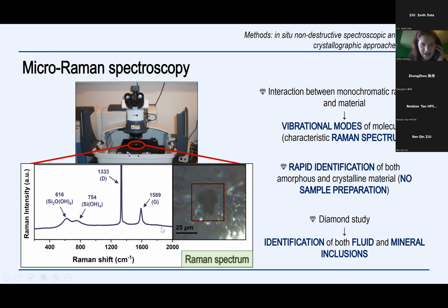And as you can see here, the Raman spectrum consists of a series of Raman peaks or Raman bands, and each Raman peak corresponds to a particular vibrational mode of the molecules that compose the analyzed material. The Raman spectrum can be considered a fingerprint of the material that we are analyzing. For this reason, micro-Raman spectroscopy is used for the rapid identification of materials, both amorphous and crystalline. This is very important. Another important thing is that this method does not require sample preparation.